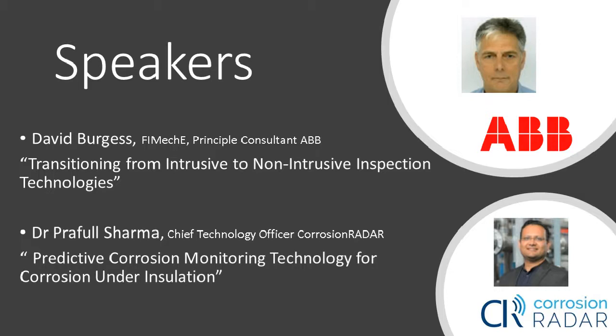That's a very good question. I believe this is still predictive, because the corrosion which is being detected by the sensors is on the sensors themselves. They are coupons, so to say, and they detect the corrosion at a very early phase. Say, for example, if the corrosion rate is about 0.1 millimeter per year, which is a very low corrosion rate, this corrosion is detected within 6 months. Normally, people will not even notice this level of corrosion, even after a year or two.